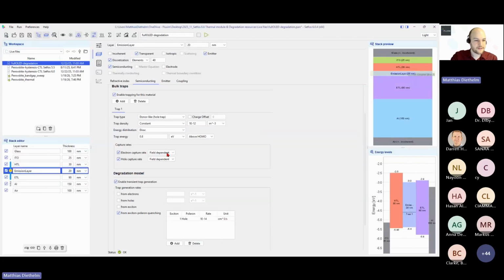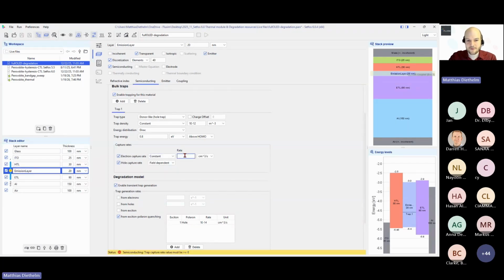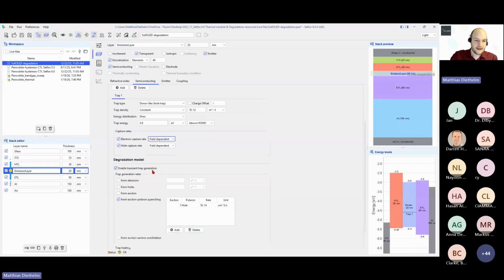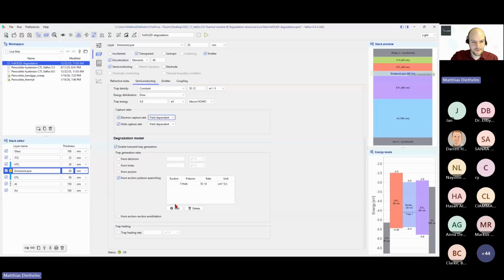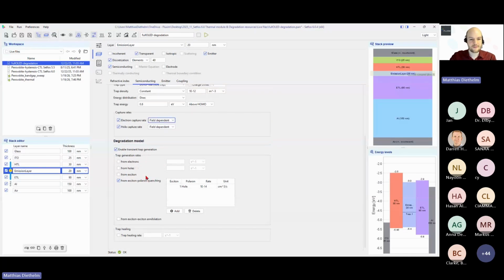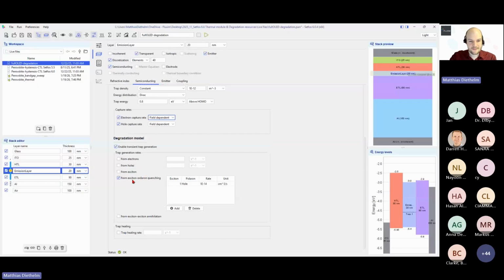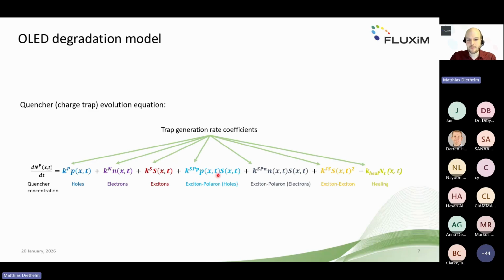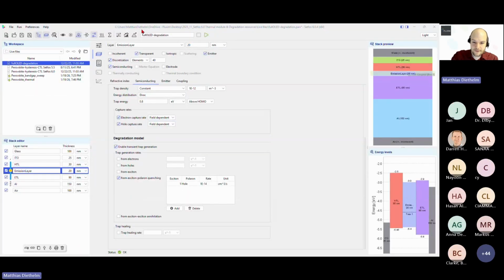So at the moment there is a model based on the parameters we put into the model defined, but what you often find is also a constant capture rate. And lastly, here is the degradation model, where you can choose which events lead to trap sites. And what you see here is what's defined is exciton polaron quenching for holes. So if we look into this equation here, that's just the light blue part, which is now generating trap sites, quencher concentration with time. So we can run this model or this file here and play around with it.